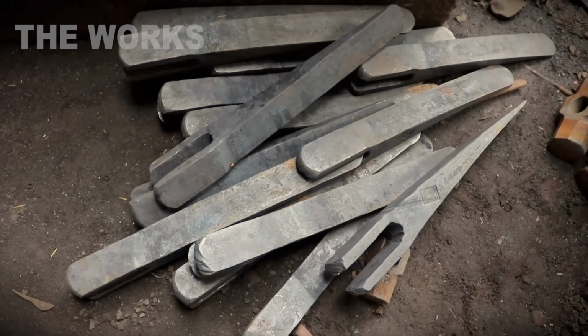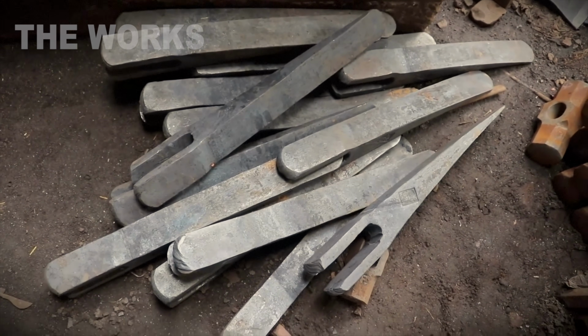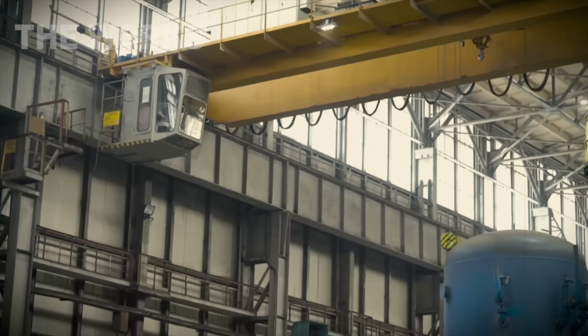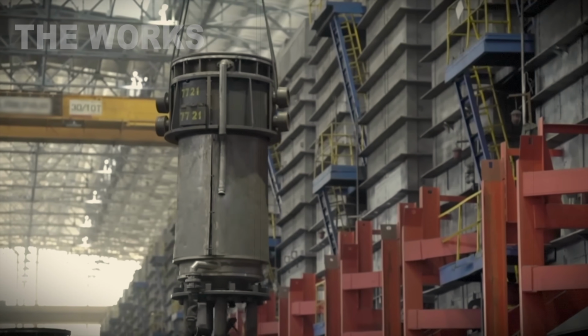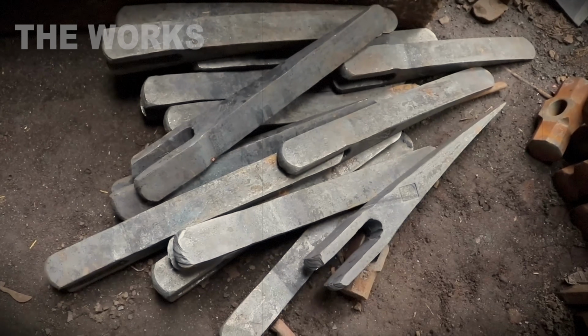Wear test. The tooth gets abraded with quartz sand of 500 micrometer grain size, at 5 bar pressure for 100 hours. That's equivalent to 1,000 hours of operation. The best teeth lose less than 0.5% of their weight.